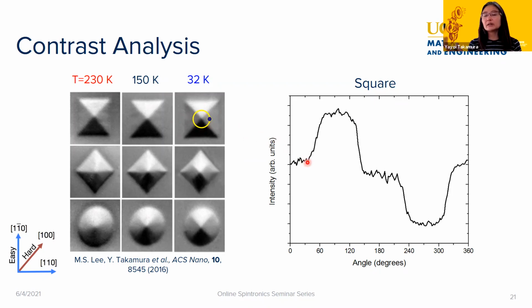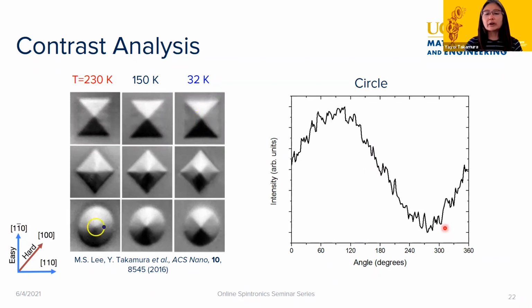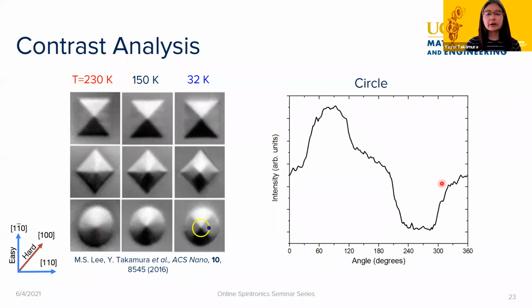we know that it should be a Landau structure, so 4 distinct magnetic states. And that's what we see. We get the gray, white, gray, black, so a step function, as we expect. Then we went to the circle one. First we start with the circle at high temperature. I said that we should see a cosine dependence as the magnetization circles around, and you can see that's what we have. We have a cosine dependence.